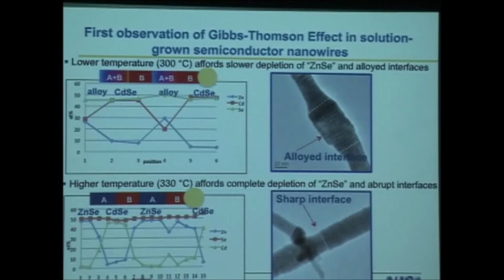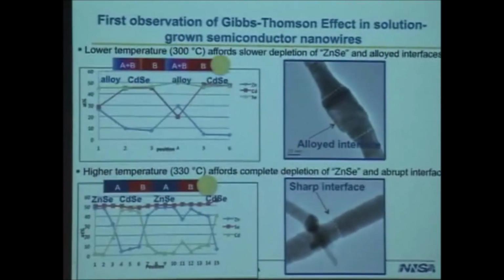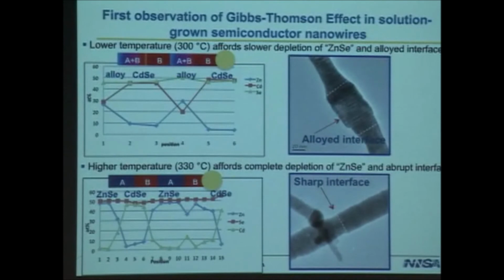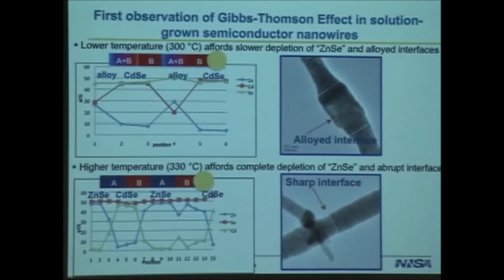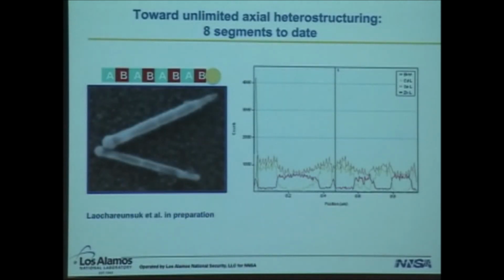A small change of 30 degrees, and what we find is we're not able to achieve clean AB-AB structures. We actually never fully get rid of the zinc selenide, for example, in the wires. And so we have a clean system and an alloy and a clean system and an alloy. In contrast, with a higher temperature and faster, we bump up the growth rate of the zinc selenide, we're actually able to achieve nice sharp interfaces and clean zinc selenide, cadmium selenide, zinc selenide, cadmium selenide interfaces or heterostructuring.